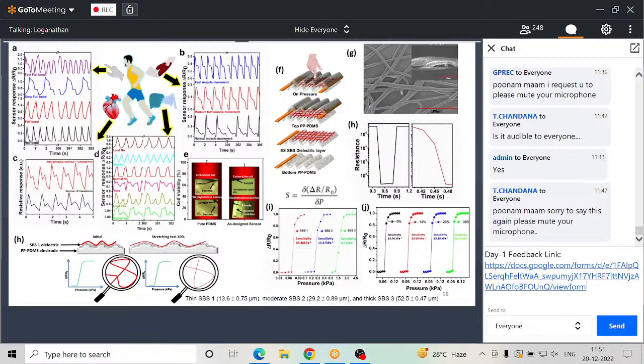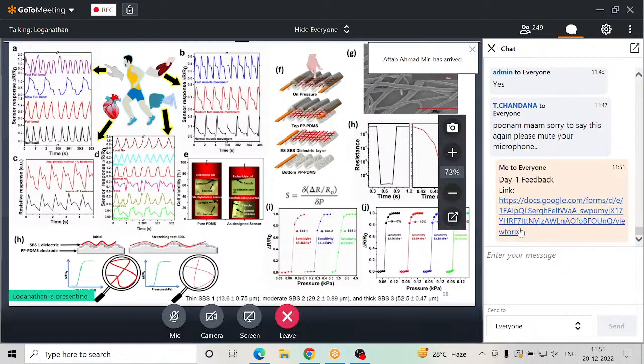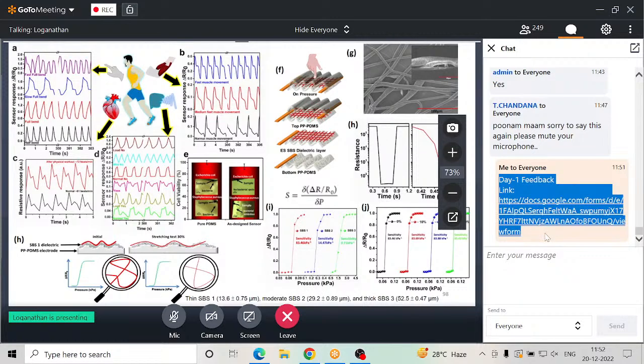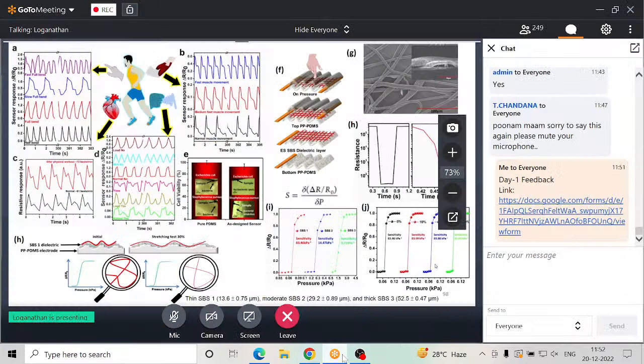And we also form strain-sensitive pressure sensors. So here we can see how fast it is. It can respond very fast, within 30 milliseconds. And here we can see the sensitivity is retained even after 30%, like 0, 10%, 20%, the pressure sensor remains the same. So their performance is quite good. And this is the schematic to show why there is a small deviation after 30% in the resistive changes.